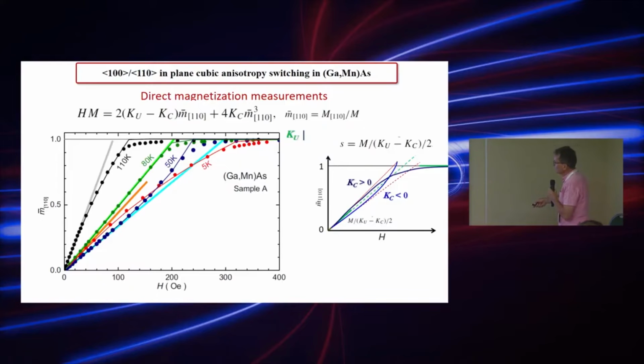So when we are at 5 Kelvin, these are the red points. We've got concave curvature with this initial slope. Then we go to 50 Kelvin, blue points, and this is convex curvature, with this initial slope. Then at 110 Kelvin, we've got again concave curvature. And this is very interesting. At 80 Kelvin, the curve goes straight nearly to the maximum value of M equal to 1. So obviously, this linear relationship at 80 K says that at this temperature the cubic constant should be nearly 0, because we have only this linear relationship.